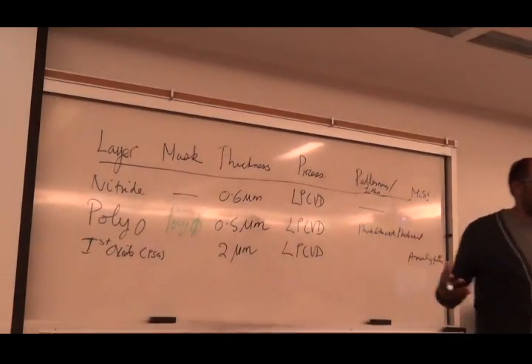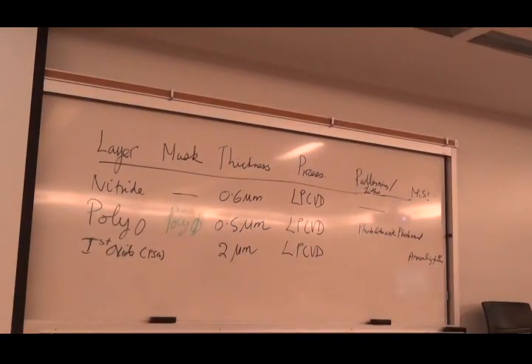for 1 hour. Annealing means, because when you combine a high temperature process with a room temperature process, you're going to have a mismatch. So you want to slowly raise it to 1,000 degrees Celsius, anneal it for a couple of hours, bring it down, then the stress is kind of distributed. Otherwise, you're going to have all this kind of shriveling action.